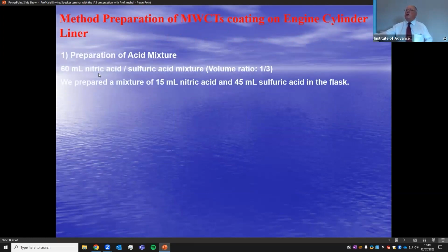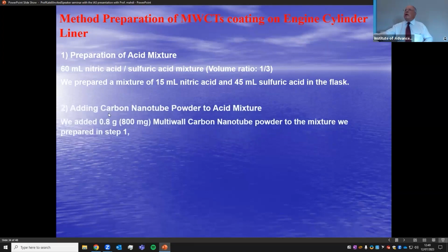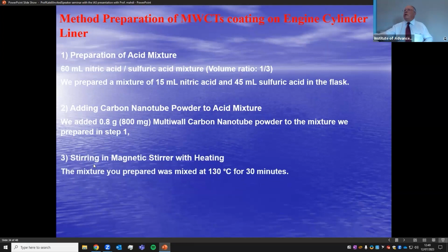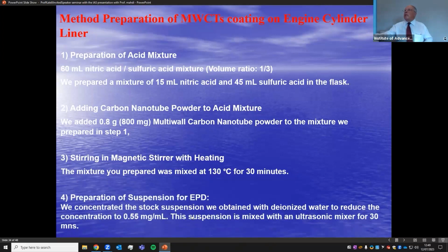So the preparation is first of all mixing nitric acid, sulfuric acid mixture. Then adding carbon in that mixture, and stir in a magnetic stirrer at 130 degrees Celsius for 30 minutes. So you obtain one solution. Then after you add very small drops of this solution in deionized water. Then you can do EPD process.